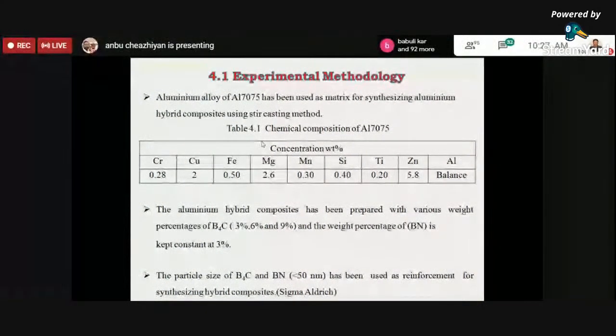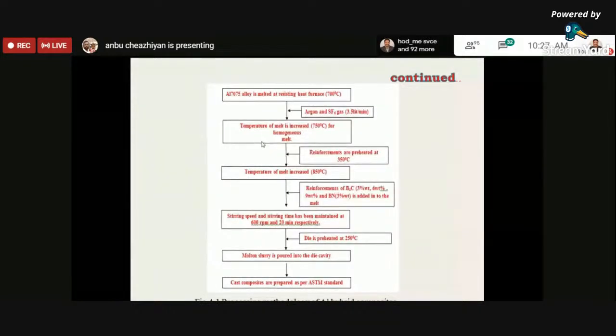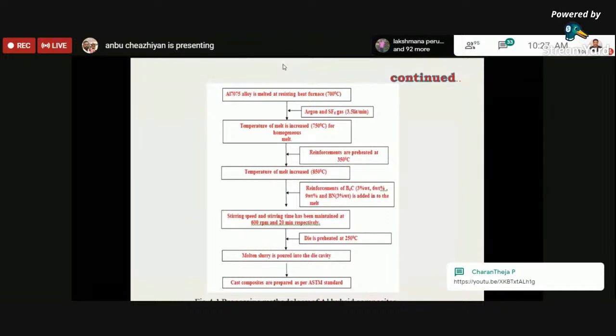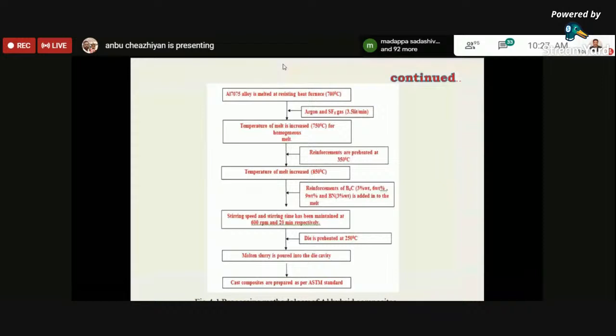We have obtained it from there, and that is used as a reinforcement. So these are the processing methods that were followed for synthesizing aluminum hybrid composites. Al7075 alloy is melted in a resistance heating furnace at 700 degrees centigrade. Since there is magnesium in the alloy, it should not be oxidized, so we have gone for an inert atmosphere. We supplied argon and SF6 gas at a minimum of 3.5 liters per minute. Since magnesium enhances the wettability of matrix and reinforcement, that should not be lost, so we have gone for a closed environment setup.